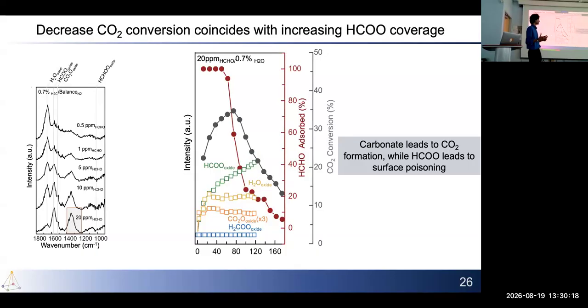So our hypothesis was that formate is the one poisoning the surface at higher coverages, and it is the CO3 intermediate, which forms initially at lower coverages, that is responsible for the CO2 formation. We wanted to test this out.